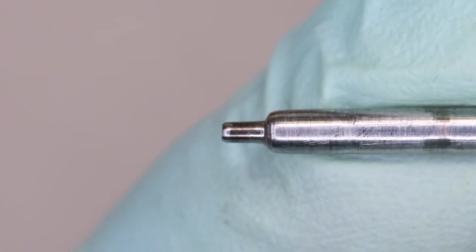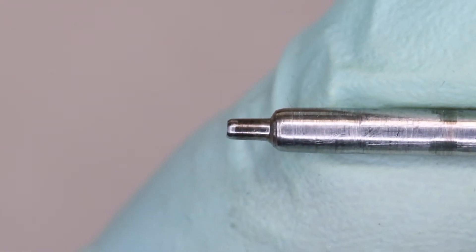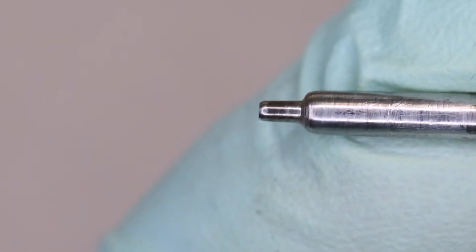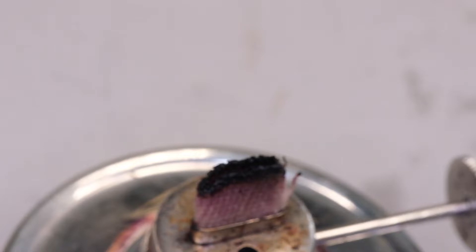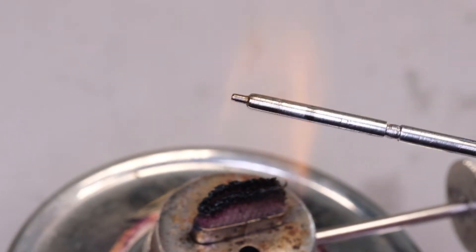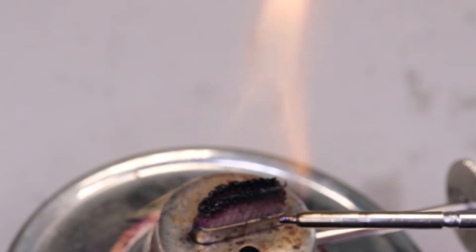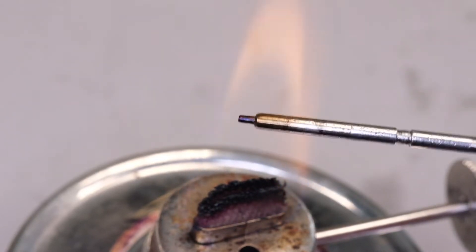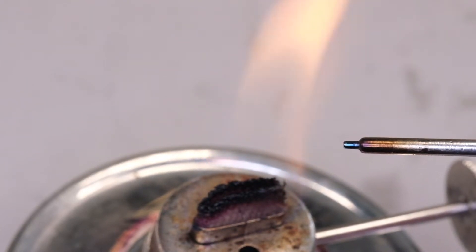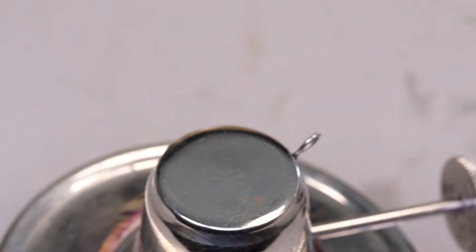It's not massively out, if you like. However, it would be useful if that arbor was about half a millimeter longer. We can see the pivot here looks okay but it's short and a little bit tapered, although I won't get too excited about that. So the next thing to do is to let down that pivot—that is, to anneal it or soften it slightly. It's just going to make it a lot easier to work. I do that in a spirit lamp flame and heat the pivot and the end of the arbor until it turns blue.